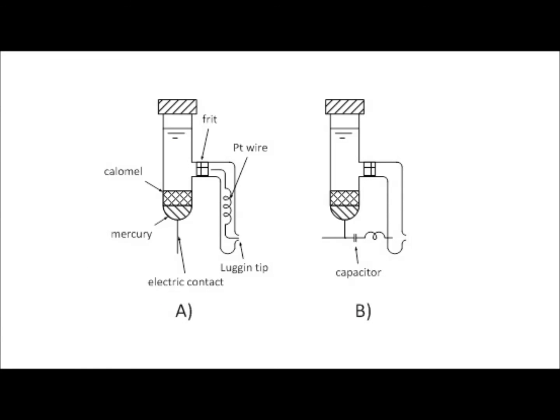Last comments on electrochemical impedance spectroscopy. There have been arguments about errors introduced to measurements by the reference electrode. The reference electrode assembly on the left labeled as A has been described as the one used by publications that claim to find a constant capacitive behavior at high frequencies.